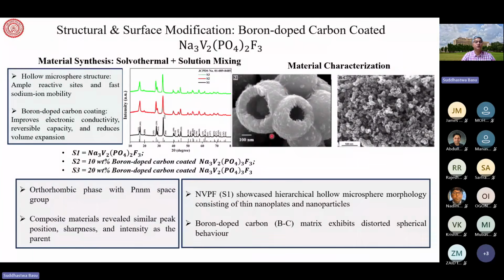So we took NVPF, which we are showing you here. We have then coated it with BDC. S1 is pure NVPF, sodium vanadium phosphate and fluorophosphate, S2 is 10% BDC coated sodium vanadium fluorophosphate, and S3 is 20% boron doped carbon coated sodium vanadium fluorophosphate. So this is a kind of hollow structure which is coated as shown here, and X-ray is done to find out that we have perfectly got the NVPF structure that we wanted, S1, S2, S3, and the coating that we wanted.